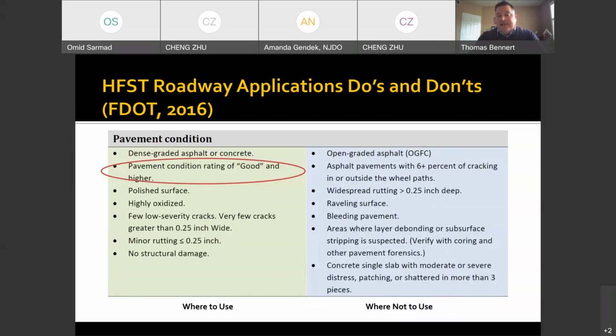One of the things, though, in selecting, I guess, projects that would require HFST is the pavement condition. And there are some pros and cons of where to use and where not to use. And this is a nice table that Florida DOT put together around 2016 on what pavement conditions are good and what pavement conditions are not good. For example, the not good, we're not going to want to put this on open graded friction course. Pavements with significant cracking or rutting or raveling, areas where we would generally see issues with any sort of bonding to it, like a bleeding pavement, areas that have staining, maybe due to oil spills, et cetera, that sort of thing. However, conditions that would be a good candidate would be typical dense graded asphalt or typical concrete surfaces.